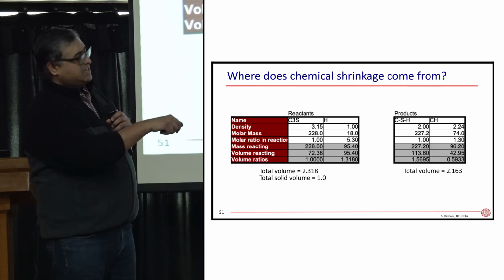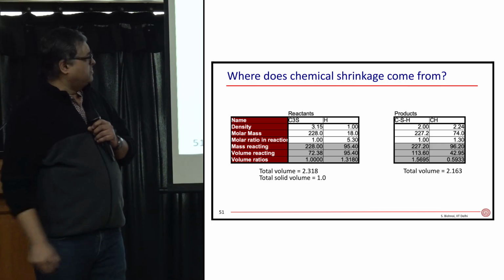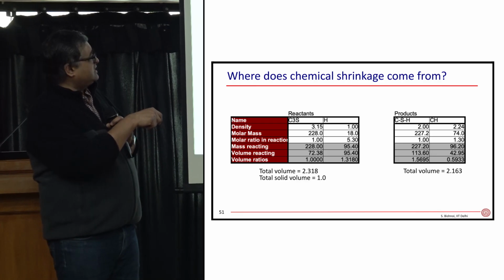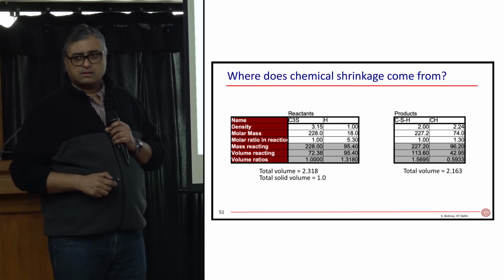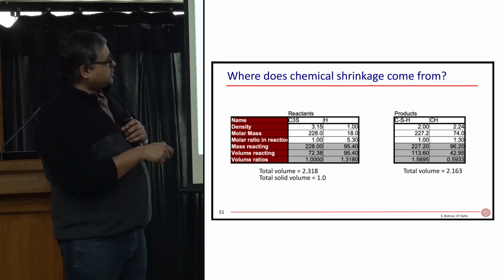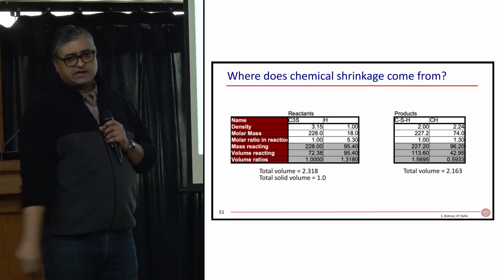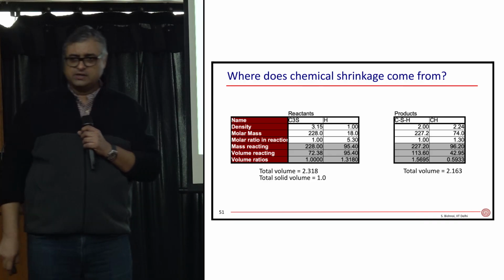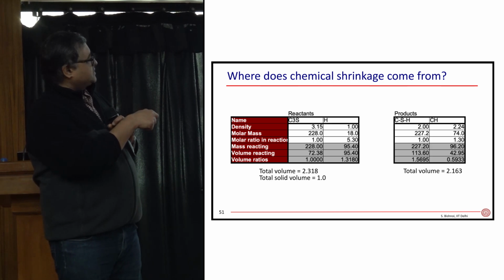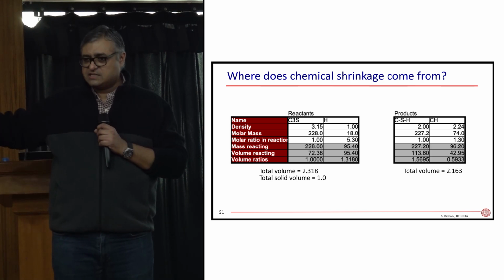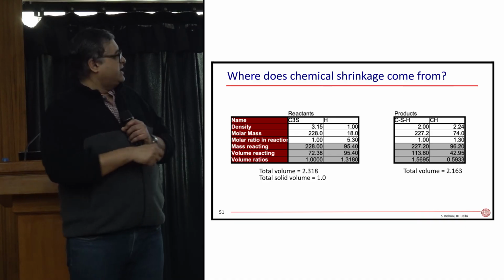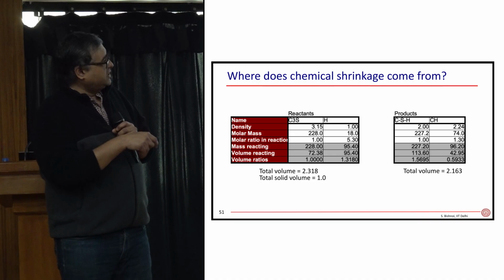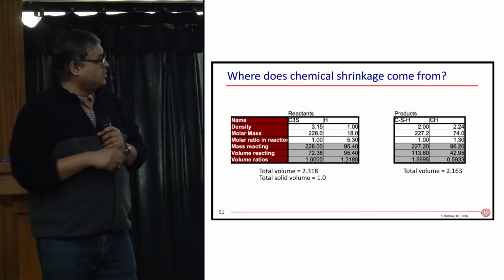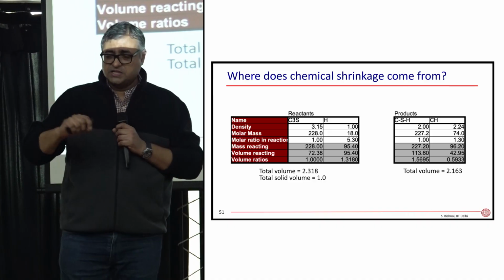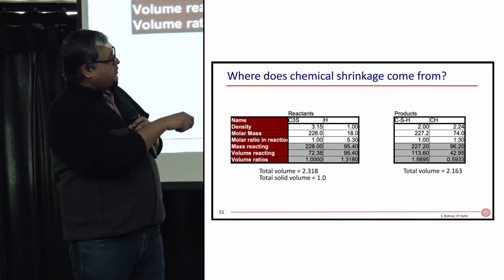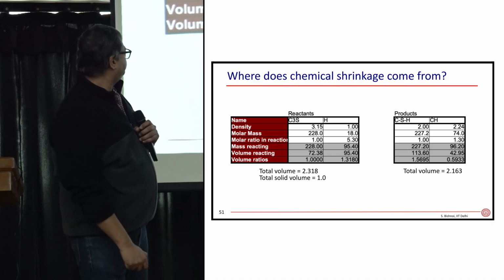If I list down the densities of those materials, or the specific gravity, in gram per centimeter cube, it's approximately 3.15 for C3S. What is it for water? 1, at a certain temperature. CSH is around 2. Calcium hydroxide is around 2.24. Now, if I find out their molecular masses, CaO whole thrice plus SiO2, if I add all the molecular masses, it comes to 228. 18 for water, calcium hydroxide is 74, and CSH comes to, if I assume the composition of CSH is C1.7SH4, 227.2. This is what it comes to.